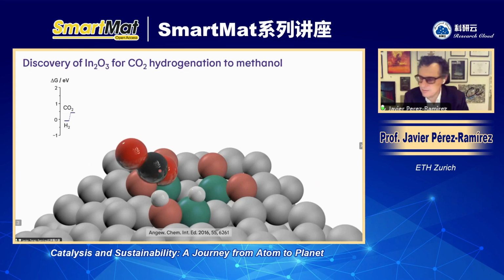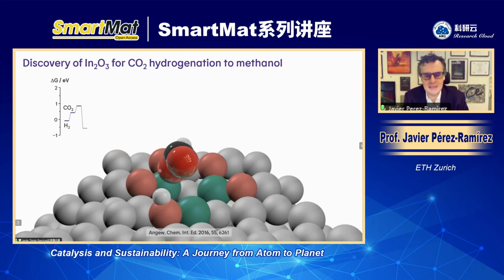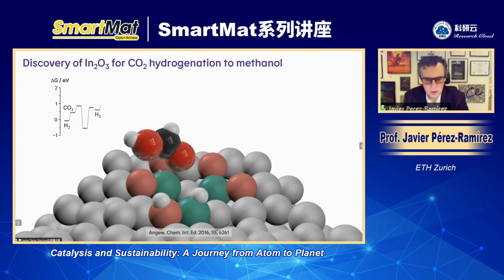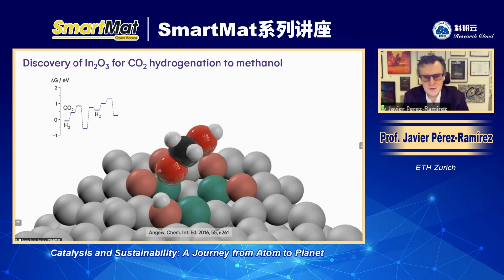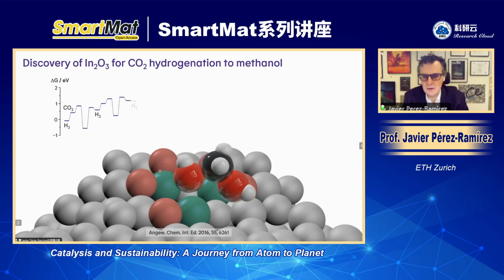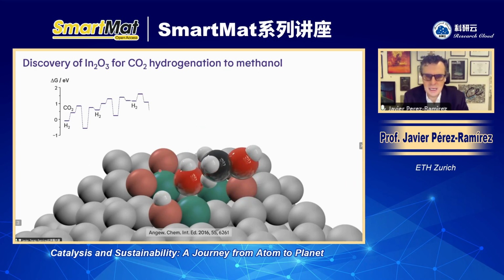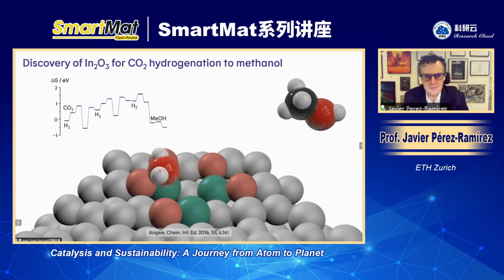And what happens next around this vacancy, very well discretized vacancy, is that there are addition of 3 moles of hydrogen to the CO2 moiety that goes through different intermediates until you form in a very selective manner methanol and water. And this is by far the most selective catalyst that exists today at reasonable levels of CO2 conversion to hydrogenate CO2 to methanol and not producing CO as product of the reverse water-gas shift reaction.